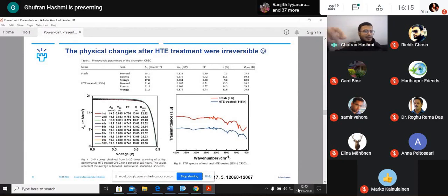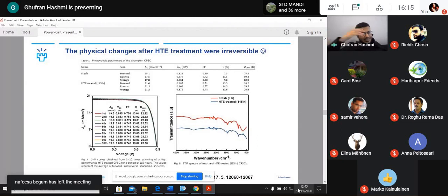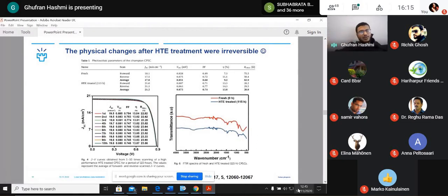And then there was also a concept of hydrate formation, where the water molecule could be attached in the perovskite crystal. So it was suggested to perform some kind of FTIR spectroscopy analysis. Somebody did it in this contribution. What we found was that there were no chemical structural changes in these crystals. So this means that there was a physical growth that occurred in between the perovskite. That amazingly surprised me. How is it possible?